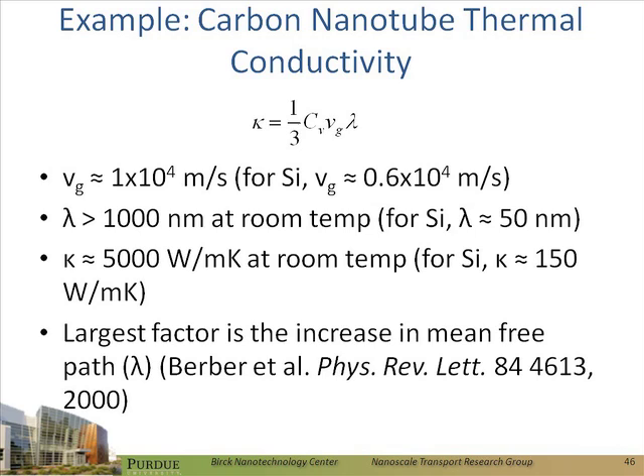Carbon nanotubes. You probably know that carbon nanotubes are fantastic electrical conductors. You may or may not know that they're also really, really good thermal conductors, about as good as any solid material. And the reasons are different, at least in one sense. The phonons dominate the transport of heat in carbon nanotubes, even in metallic carbon nanotubes. It gets back to one of the questions earlier about electrons. The electron density in carbon nanotubes, even metallic ones, is not high enough, near the Fermi level at least, to have a significant contribution to thermal conduction.